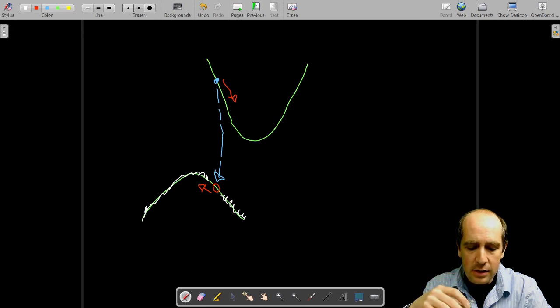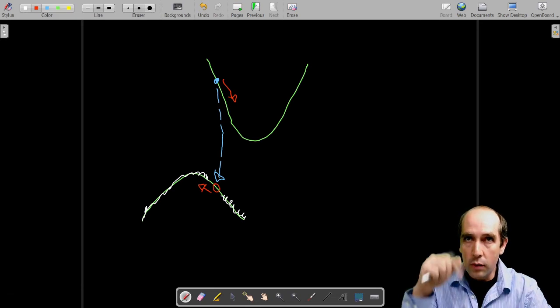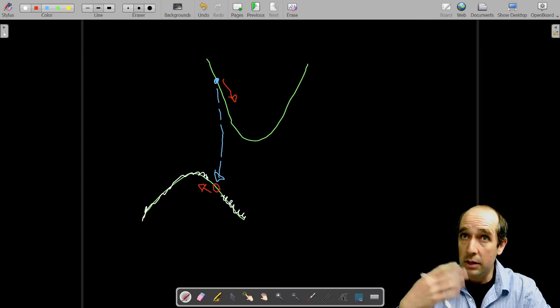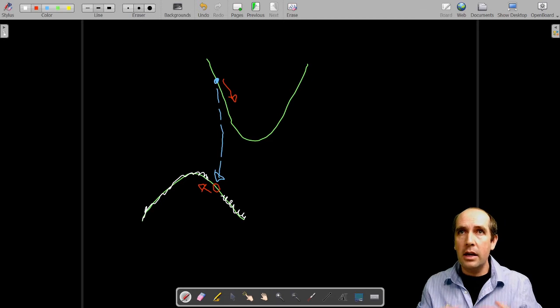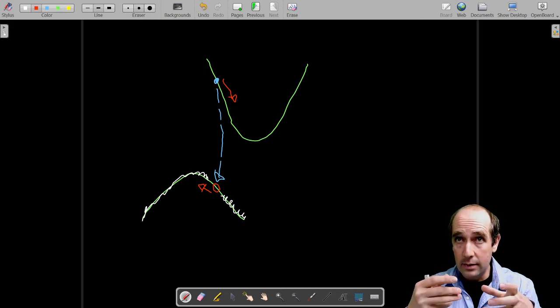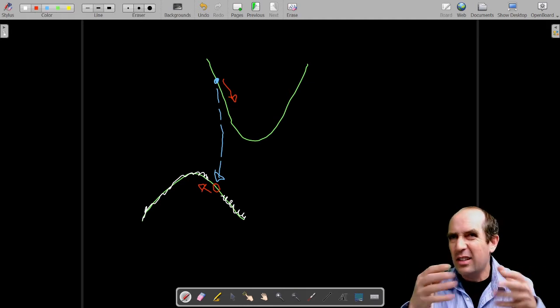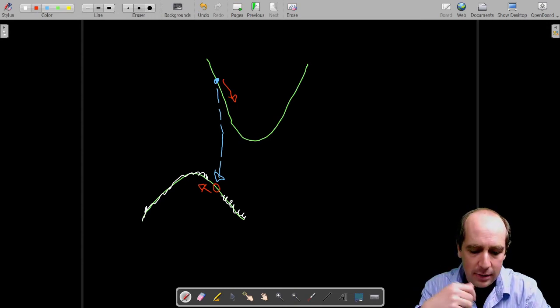Basically the electron and the hole here have two choices: either to recombine by emitting a photon with a lot of energy, or they can give their momentum and excess energy to the lattice, producing vibrations in the lattice, so basically producing heat, increasing the temperature of the lattice.